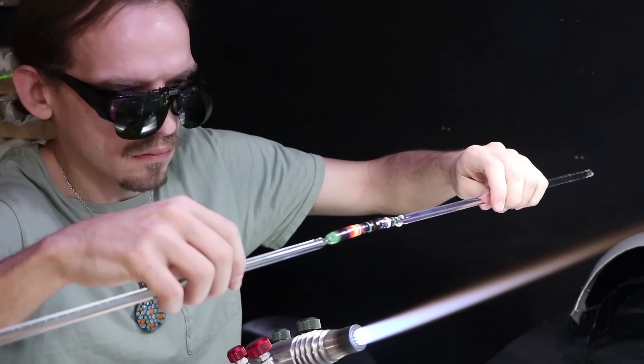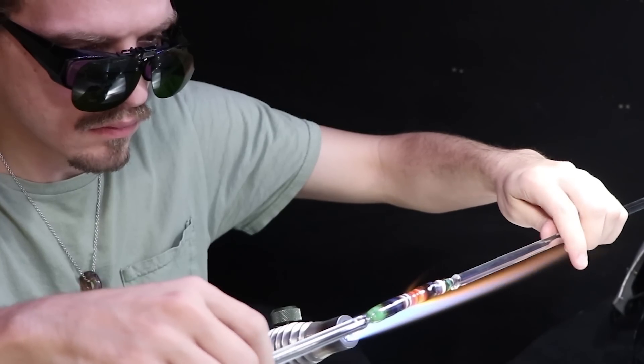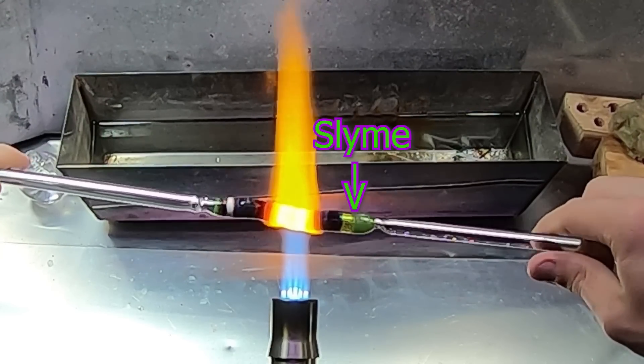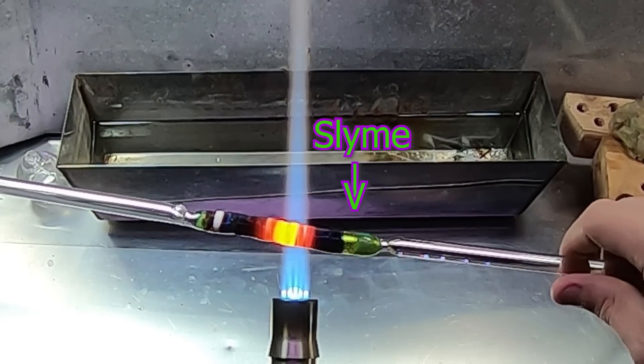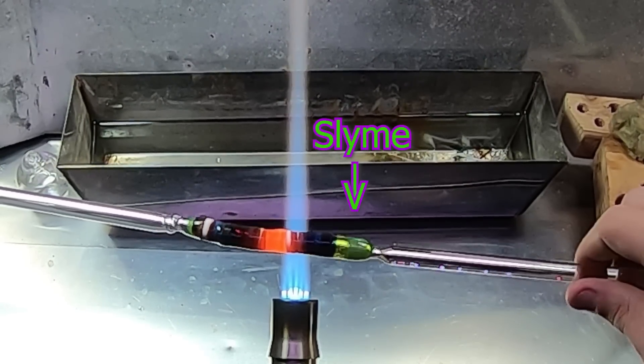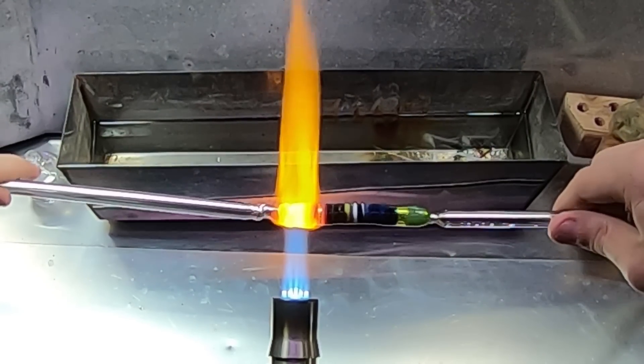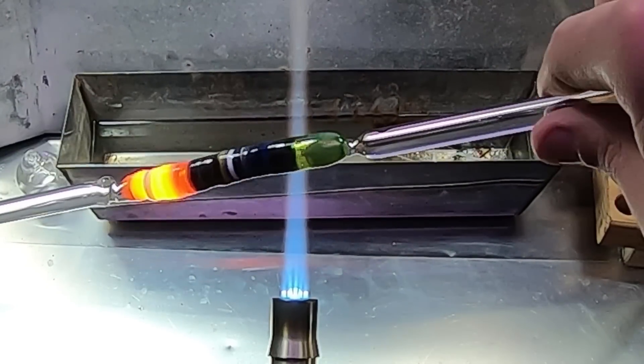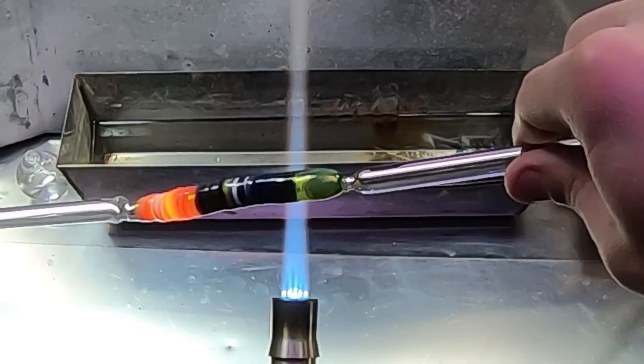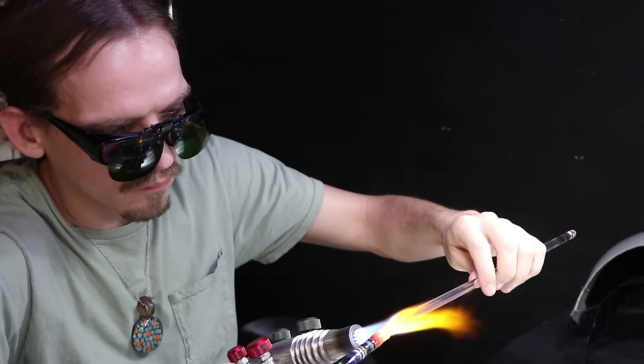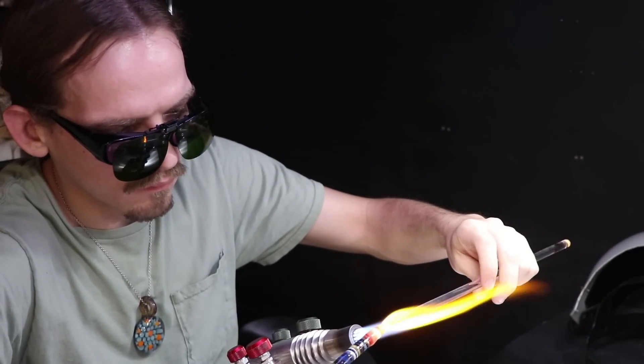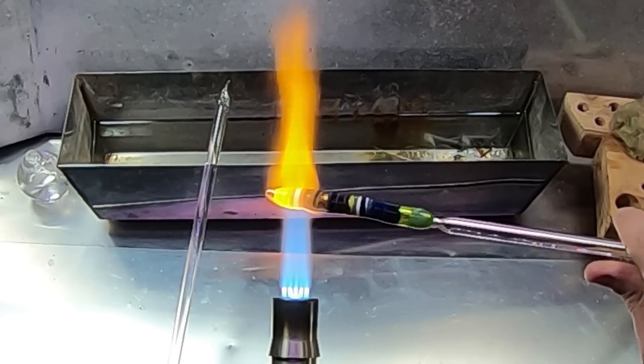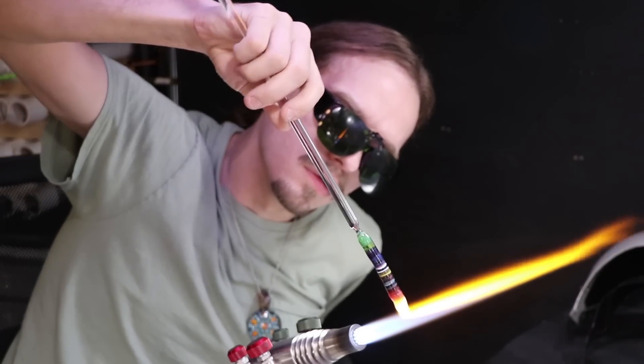I do have a few extra bits on here. I have some white out from tag glass, Trautman Art Glass, and also some Slyme. It's a very vibrant green color, kind of reminiscent of the slime you see in Ghostbusters. It starts off pretty opaque, not quite like a solid color. If you work it slow in a low heat you can keep that opacity to it. But the way I think you're supposed to work it is to heat it up enough to start to fume and burn off that outside layer to reveal the transparent green undercoat. So it's really great in shaping work along with the other silver striking colors: the amber, purples, and reactive ones. The fact that you get multiple colors or slightly different shades of the same color kind of gives it a little bit more texture in the finished work.